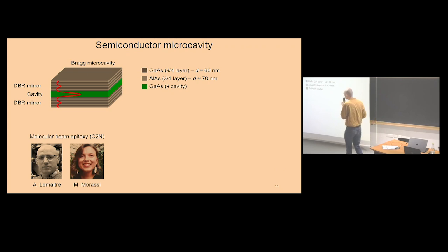Due to this index of refraction mismatch, you can organize interference effects at each interface. And in fact, if you realize what is called the Bragg condition, which is that each layer has to be of optical thickness lambda over 4, a quarter of the wavelength, you will fabricate a very good mirror.